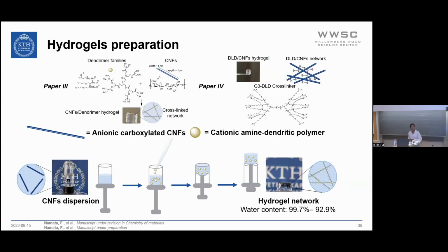You put your dispersion, you put your solution of either dendrimer or DLD, you leave it overnight, refrigerated, and the next day, you have your hydrogel. Simple as that, no external stimuli. Two components, and we have a hydrogel with a very high water content.